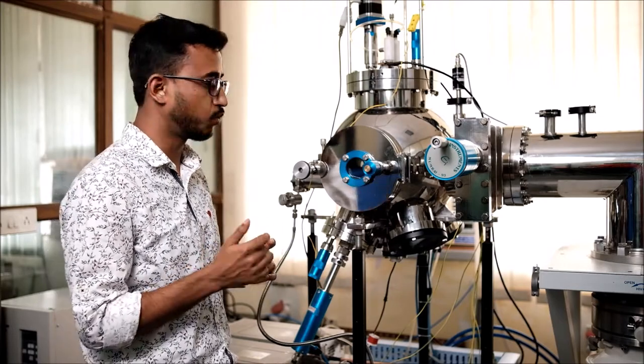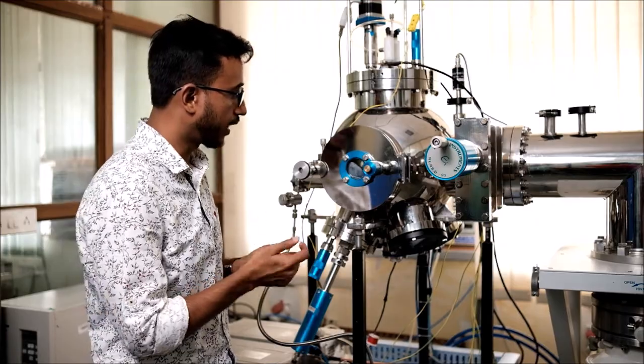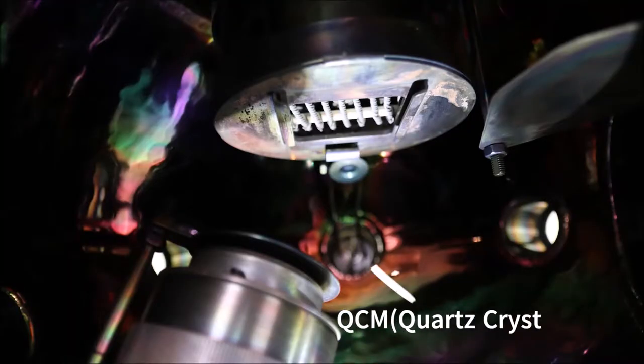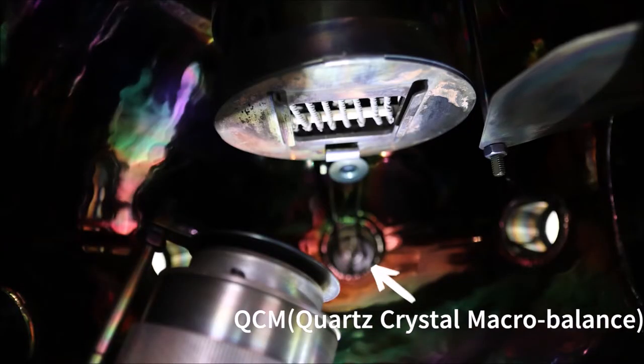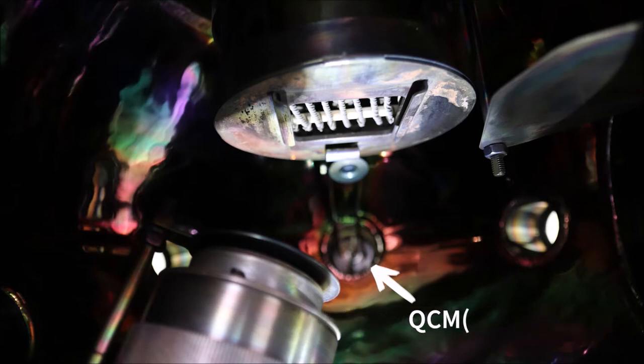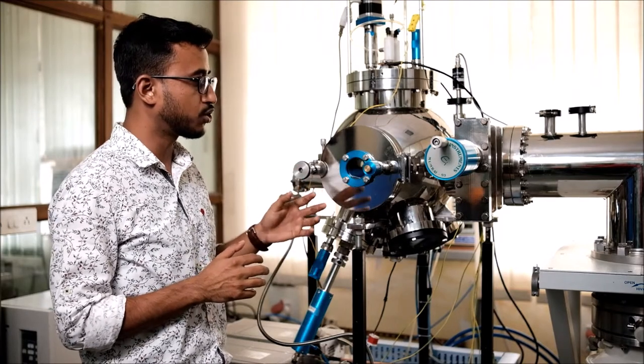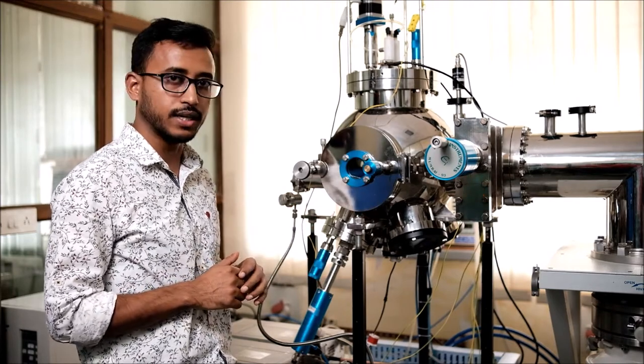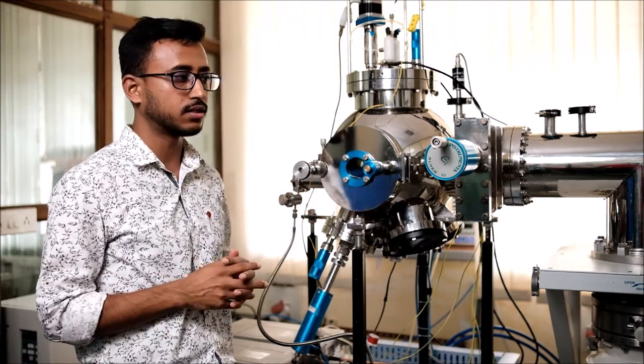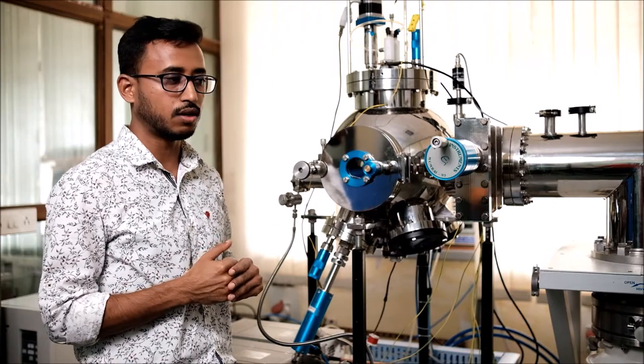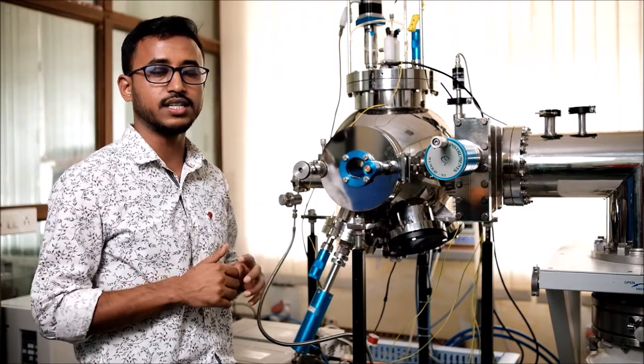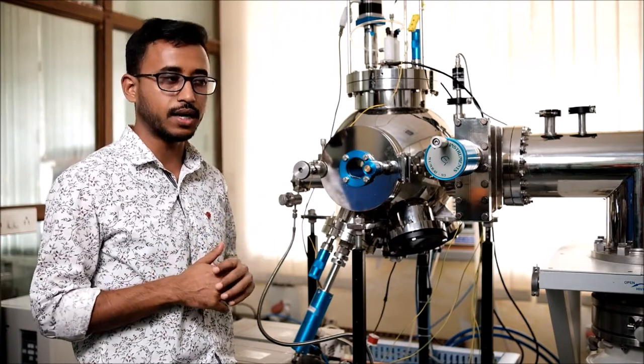This also rotates with a controller. And at the back of the substrate rotation holder, we see a disc-like structure. This is the quartz crystal microbalance system. This is used to monitor our film's thickness. This actually operates on crystal oscillation. It has a natural frequency of 6 megahertz.